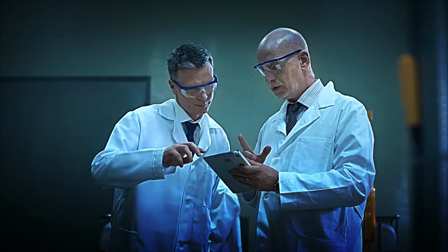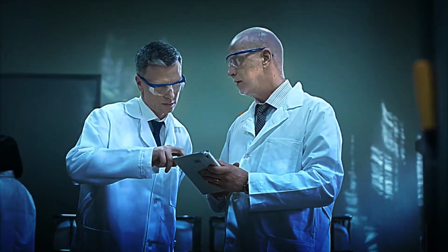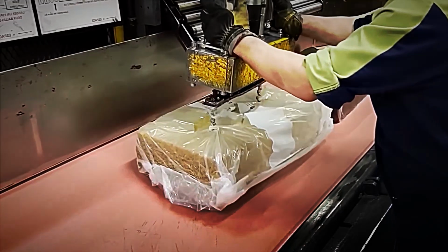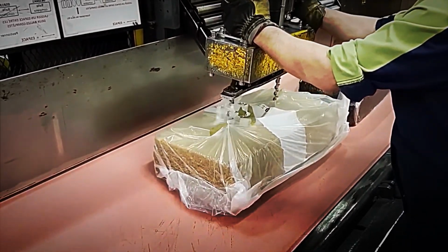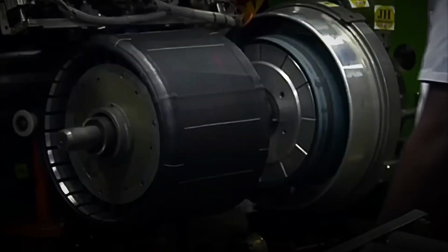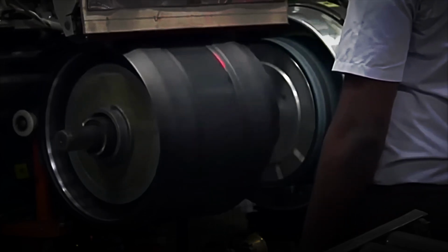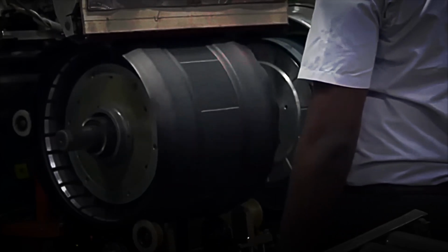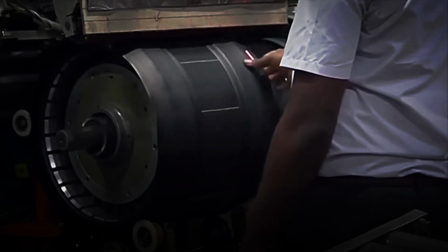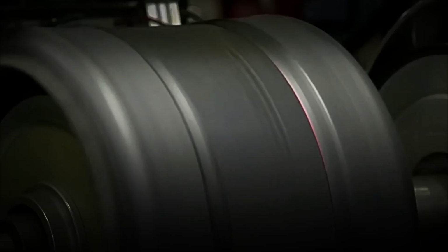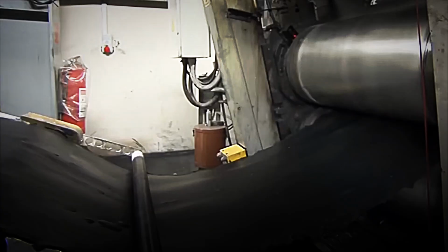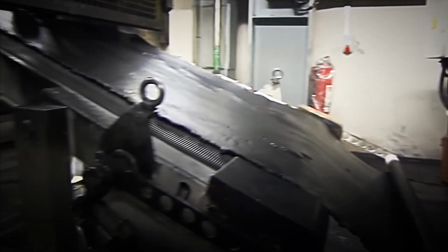With all subcomponents ready, they are mounted on a building machine resembling a horizontal lathe. On an expandable metal drum, the operator first lays the inner liner, a butyl rubber layer almost impermeable to air that replaces old tubes. Then, the carcass ply positions the beads on both sides and folds the fabric edge around them. Steel belts wrap over the carcass, and finally the tread with its shoulders is applied. A light puff of compressed air helps bond the layers. The result, called a green tire, has no tread pattern yet and has not undergone its irreversible chemical reaction.